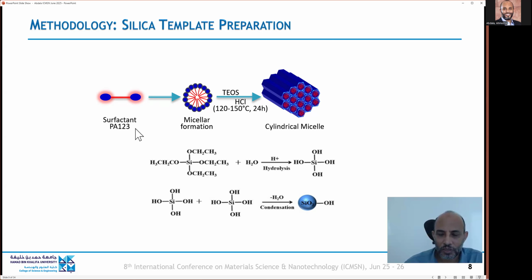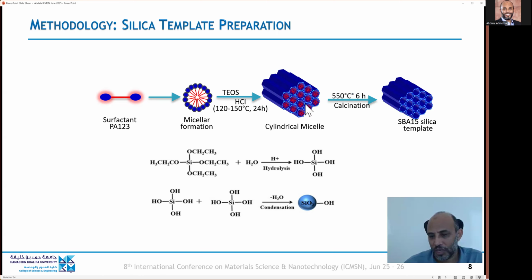The approach to prepare the nano catalyst is using a silica templating method. So first we prepare the silica template using the polymeric surfactant, just dissolving it in water, and then add the TEOS as a silicon precursor. Then through hydrolysis and condensation, we form cylindrical micelles that have silica hydroxide on the outer surface. And then we can calcine to remove the surfactant, and we end up with the silica template with cylindrical nanopores. We can control the pore size by the hydrolysis, condensation, and calcination temperature. We can control the particle size.